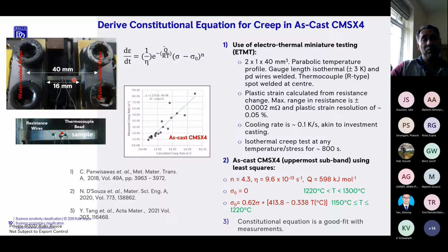One of the main advantages of using miniature testing is that you can look at the compositional effects of as-cast microstructures. One thing to bear in mind is that in miniature tests, the specimens are extremely narrow, typically 2 by 1 in cross section, much smaller than your traditional macro specimen, where the typical gauge diameter is about 6 millimeters. You've got a parabolic temperature profile across the length of the specimen.